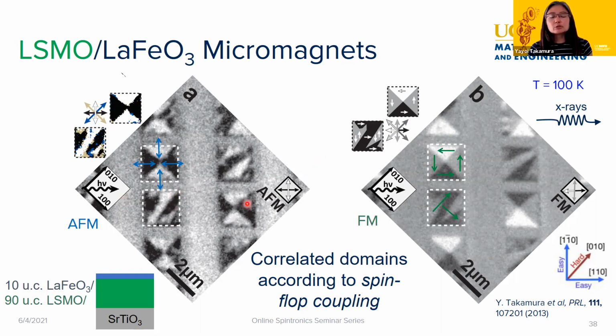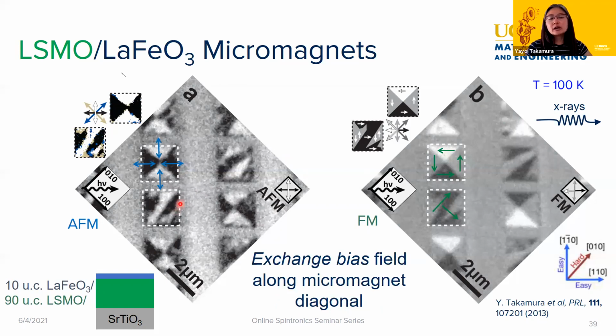And then we were puzzled as to why we get this offset of the center of the vortex cores. Why do we get these Z domains, right? So again, we did some micromagnetic simulations. What we could always tell from these is that the ferromagnetic domains have a net magnetization along the diagonal of the nanostructures, and it was basically random depending on which nanostructure we looked at. Sometimes it was going up to the right, sometimes down to the left. There was no set direction, so we know that it wasn't because there was a magnetic field induced in the microscope or some anisotropy in the sample during construction. It's really something that's inherent.